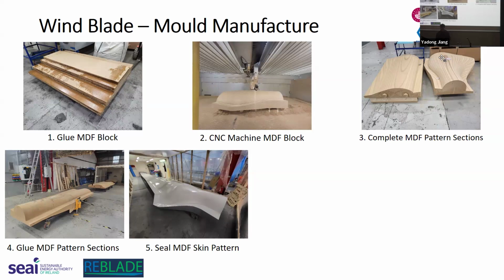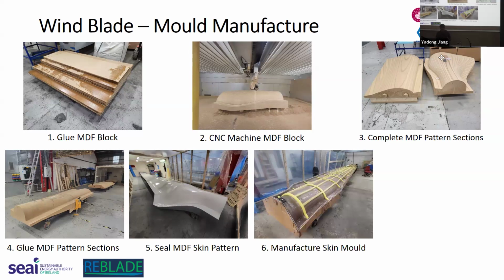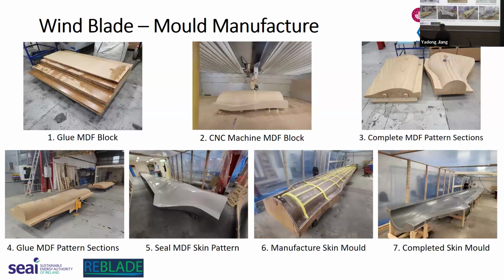So we sealed it with some gel coat, and then once the gel coat was set and polished, we started making our mold itself. So we reinforced it with some composite material, which is glass fiber and polyester resin, and then we put some stiffeners on the back of it, which you can see, these yellow stiffeners here. And then once everything was set and cured, we demold it and polish the actual mold surface itself. So you can see here in the bottom right the completed mold skin ready for manufacturing the skin component.